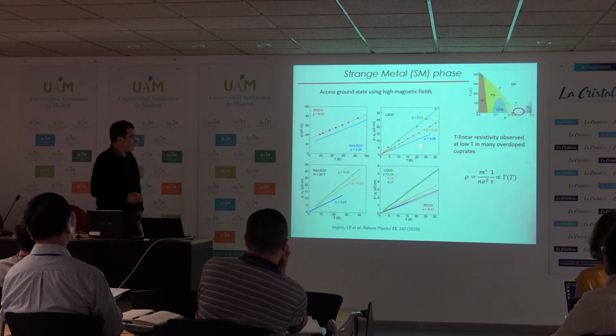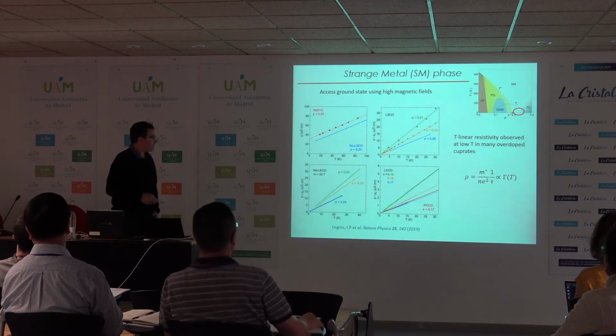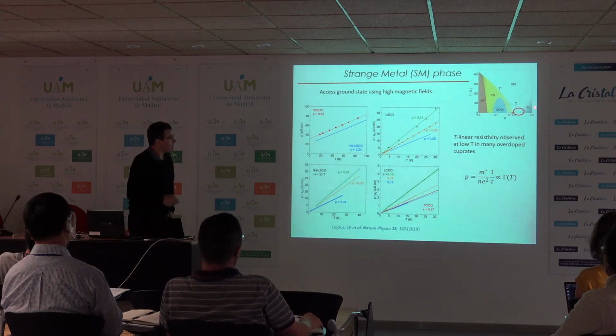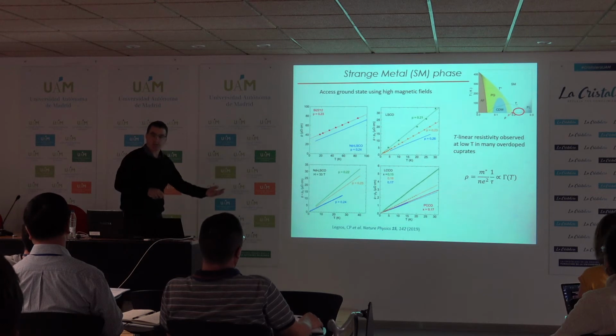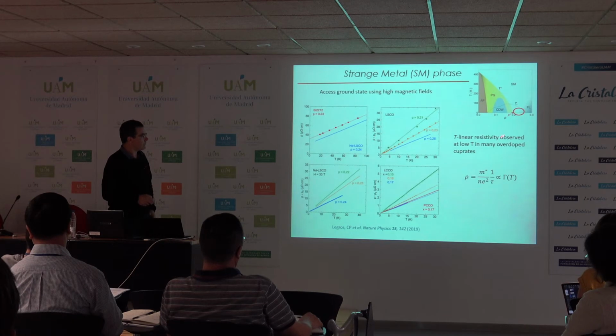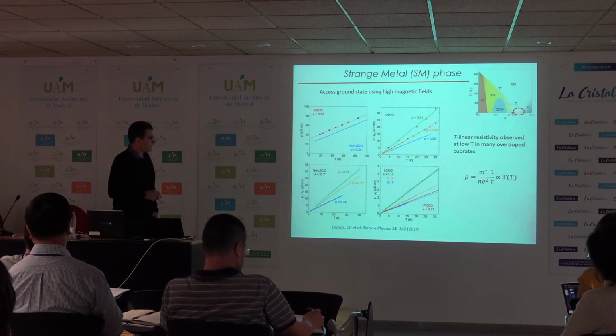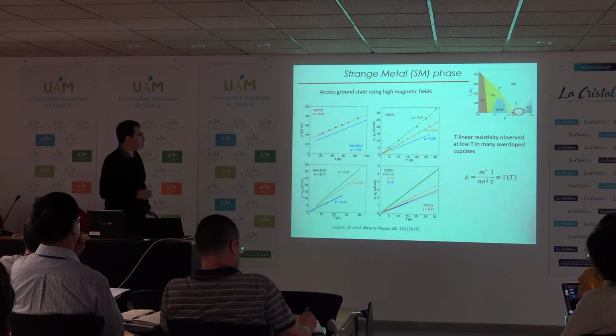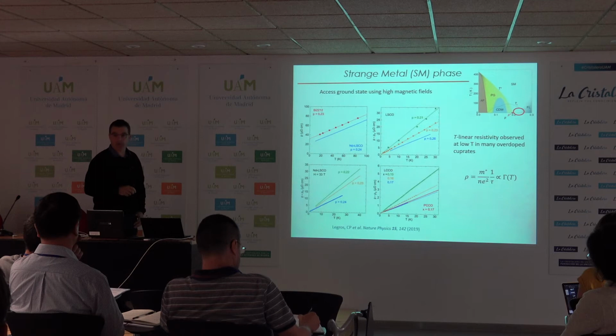And all these compounds, the doping of all these compounds, lie above the critical point of the dome. They are overdoped and in this red circle here. And as you can see, all the measurements show linear resistivity down to low temperature when you apply a magnetic field.